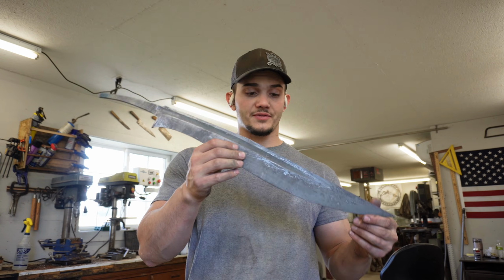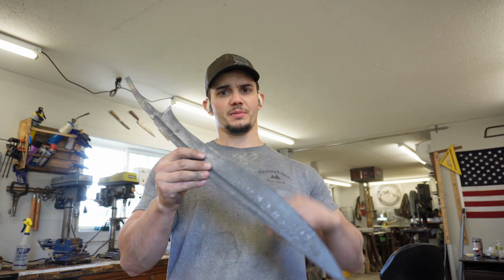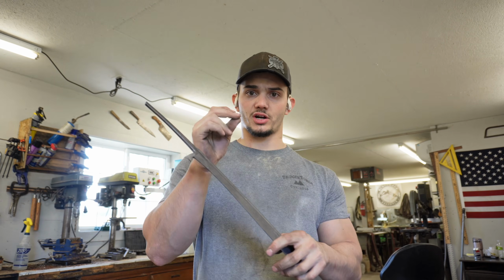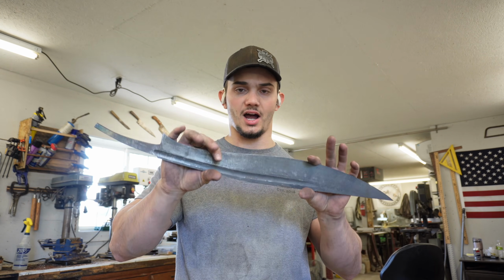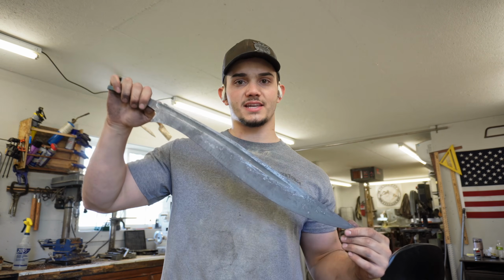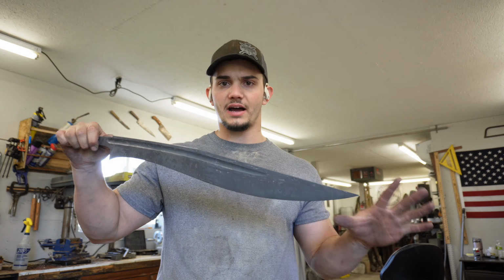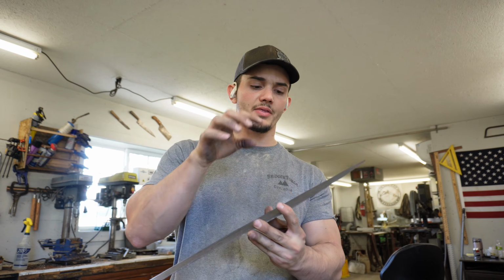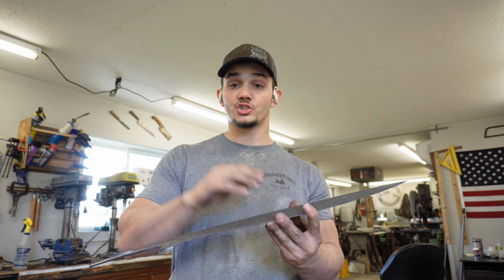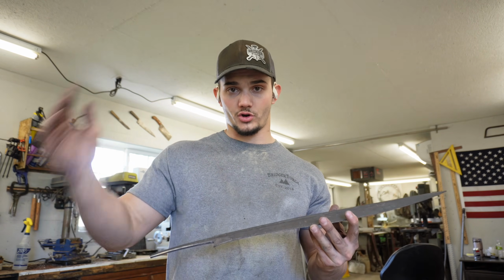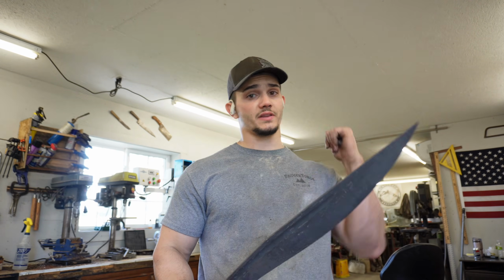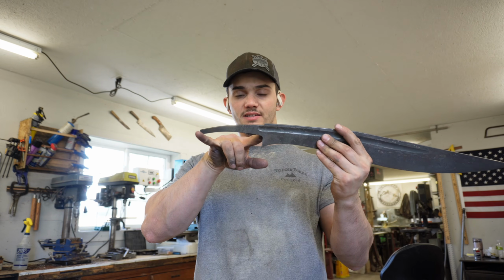So now that we have this sword completely thermal cycled, that means normalized and annealed, so the grain structure is perfect and it is dead soft, I have scraped all of that anti-scaling solution, that clay, off the outside. It kind of hardened into a shell that protected it from decarburization, so I won't have to grind as much off after the quench.